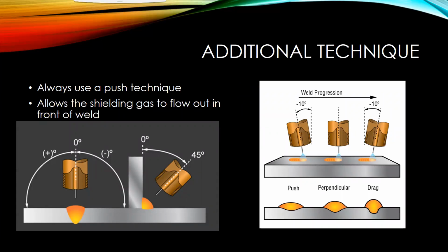Next thing I would like to talk about, we've talked about this in the past few webinars, but where this really comes into play is you always want to make sure that you're using the right technique with aluminum. Typically, you'll always want to use a push technique because as you're welding with aluminum, you really want to make sure that you get that shielding gas out in front of the weld. If you're moving from left to right in the diagram here, you'd want to make sure that your wire is pointed in the direction that you're going. It'll help that shielding gas get out in front of the puddle and protect it from any contaminants in the air. And the same applies for your work angle here. The molten metal puddle will flow wherever you point it to.